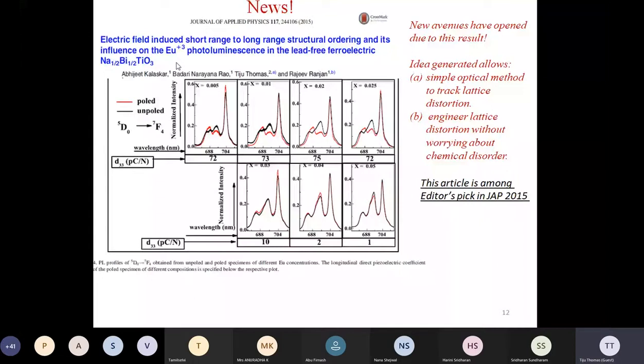And in 2015, when we reported this, at that time, the editor was very satisfied with the story because it was a little unconventional a story. Being able to spectrally tune using electric fields is known. There is electrochromism. But here is a case wherein you are tuning it not directly through some rearrangement of atoms, but through some compensation that is occurring, and you're overcoming chemical disorder related luminescence quenching. That means loss of luminescence. So that makes it very, very fascinating.